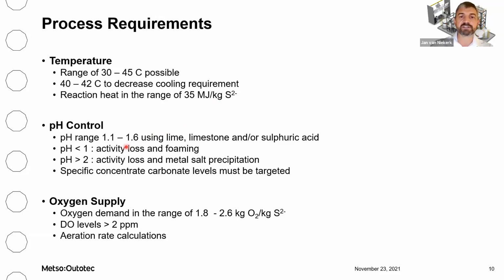The process operates also at a very acidic pH of 1.1 to 1.6, and that is normally controlled using either limestone and lime for an acid producing concentrate or sulfuric acid for an acid consuming concentrate. As I said before, the sulfide mineralogy and the carbonate content of the concentrate will determine whether it's acid consuming or acid producing.